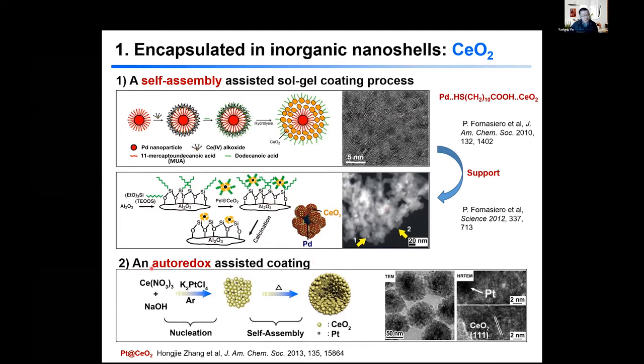Okay, another very clever way is to use this auto redox reaction, and people, for example, precipitate cerium 3+ and platinum 2+ and produce a precursor particle. And upon heating of this kind of precursor particle, there's an auto redox reaction. Basically, cerium 3+ becomes 4+, and platinum 2+ is reduced, becomes metallic platinum. And then you end up with these clusters of cerium oxide with platinum nanoparticles inside, and very small.